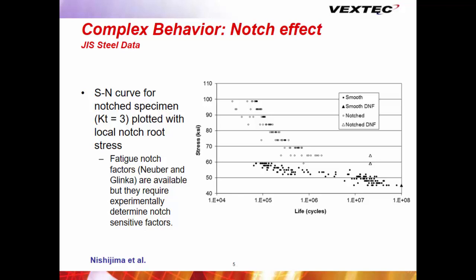So we do have to get out of this thought that there's an S-N curve or an endurance limit for a material. No, that's dependent upon all of those other Ks. Now, indeed, we've got Glinka methods and Neuber methods to capture notches, but still I have to do tests to get my parameters in those, and I've got to test multiple notch sizes. So it boils down to this: I have found ways computationally of accounting for notches by doing tests.